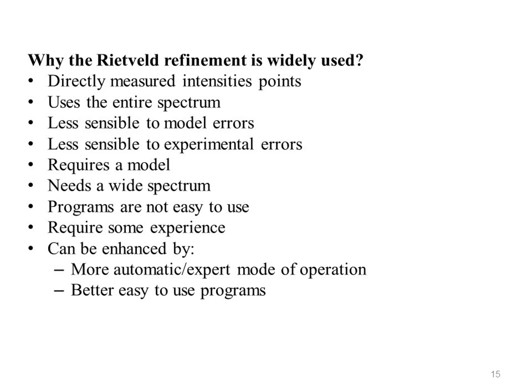Why is the Rietveld refinement widely used? It uses directly the measured intensity points. It uses the entire spectrum as wide as possible, less sensitive to model errors, less sensitive to experimental errors. It requires a model. It needs a wide spectrum. Rietveld programs are not easy to use. Rietveld refinement requires some experience, at least 1 to 2 years. It can be enhanced by a more automatic or expert mode of operation, better easy to use programs.